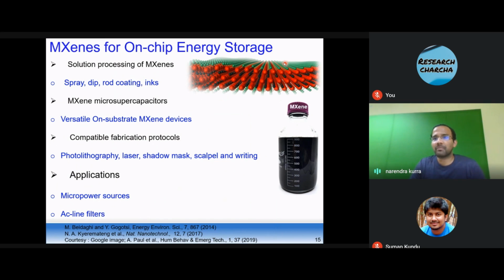We obtain MXenes through a wet chemical etching process. During that process, MXene inherently develops functional groups such as oxygen, hydroxyl, and fluorine. And because of the negative surface charges on MXenes, they repel each other, and you can get nice colloidal dispersions in water. This material enables solution processing, and it is possible to process them by a variety of spray coating, dip coating, and rod coating methods.